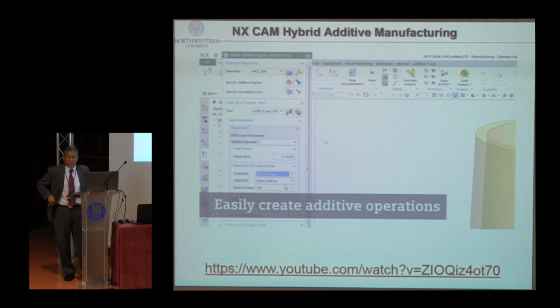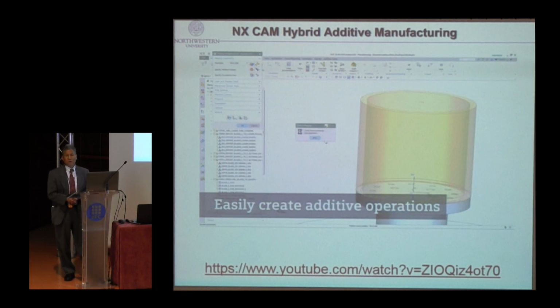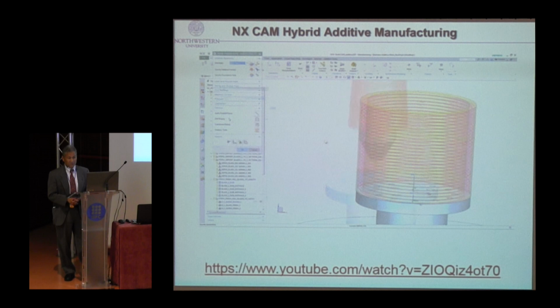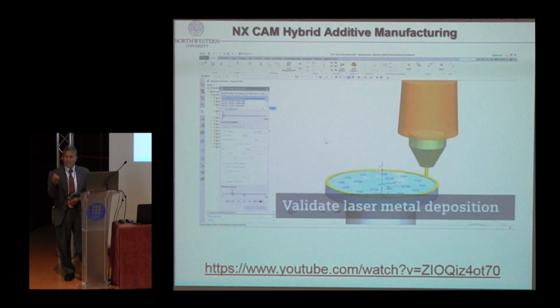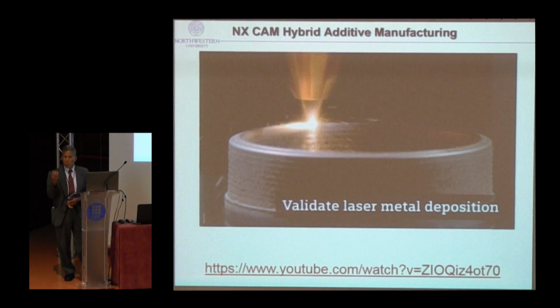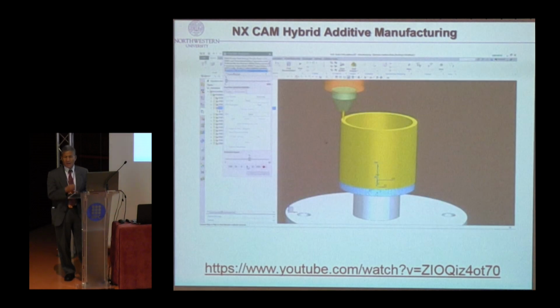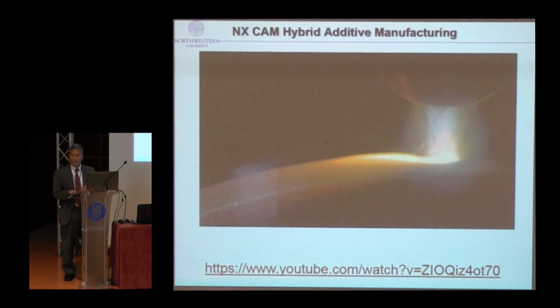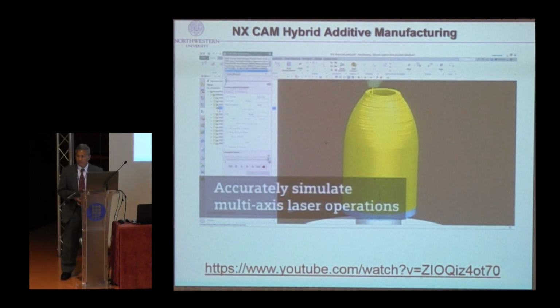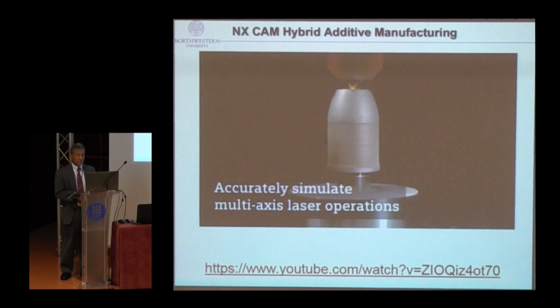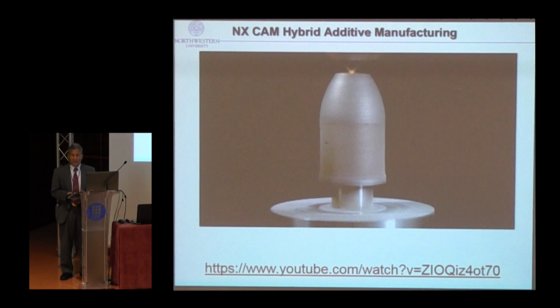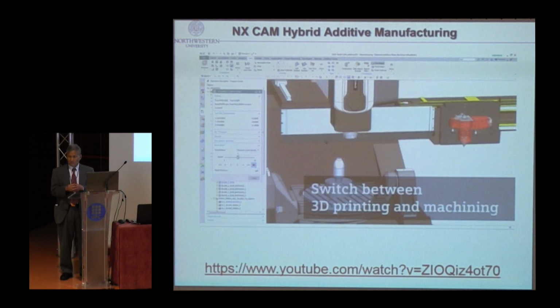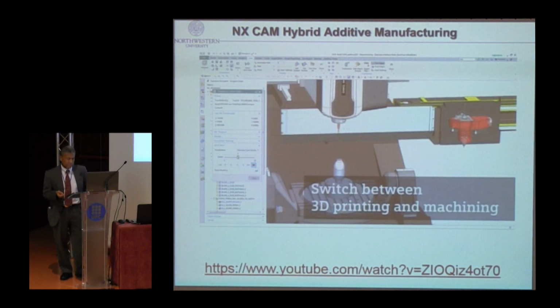So it's all computer generated. You can get a geometry pretty accurate. However, what is inside the material when you make it? What is the microstructure? How can you control the microstructure? And from that, the process changes the microstructure. And that's the reason my database is so important in this case. So you do experiment and do simulations and do online monitoring, feedback control to control the microstructure.